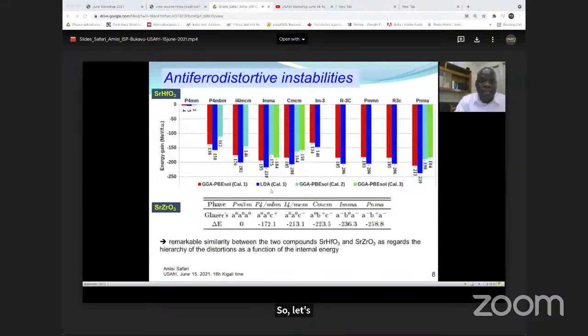So let's condense now only the rotation instabilities with various combinations. As you know, we have in phase and out of phase rotations. You can see that in phase rotation is more favorable when you condense only in one direction than in 2 and 3 directions. But the out of phase rotation is more favorable when you condense in 2 directions than in 1 and 3 directions. Even by adding the ferroelectric motion in this 3 direction distortion, whatever the functional used, we still do not observe an additional energy gain. Here you have 2 direction out of phase rotation, and here we have 2 direction out of phase rotation plus ferroelectricity, but the energy stays the same.